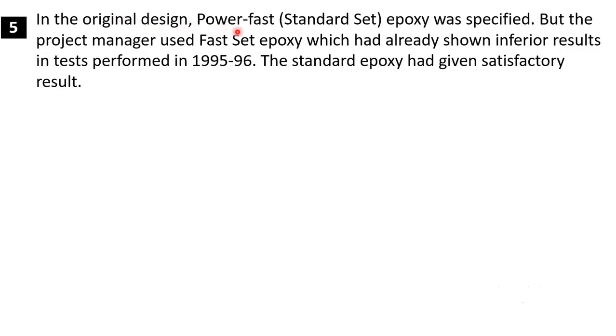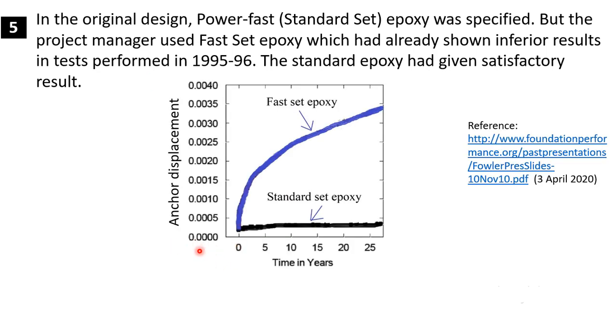In the original design, power fast or a standard set epoxy was specified for the bonding purpose. But the project manager used fast set epoxy which had already shown inferior results in tests performed in 1995-96. So the standard epoxy had given satisfactory results. So here in the case of selecting the epoxy, a decision was made to use epoxy which was inferior in quality. In this figure, it shows the creep test, where anchor displacement is plotted in terms of number of years.